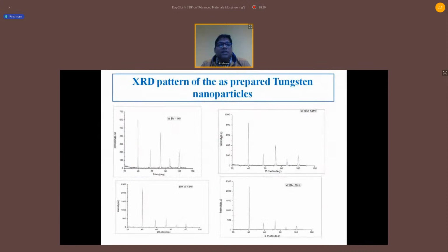Basically, the XRD pattern of the tungsten nanoparticle shows planes 110, 200, 211, 220, and 310 for different times. First is ball milling for 11 hours, and we have to optimize the milling time. We are taking commercially available tungsten powder from Sigma Aldrich, with a 16:1 ball-to-powder ratio using toluene and tungsten carbide balls. We are using a high energy planetary ball mill in our lab, and after ball milling for 13 hours and 20 hours, we got this XRD pattern for the tungsten nanoparticle.